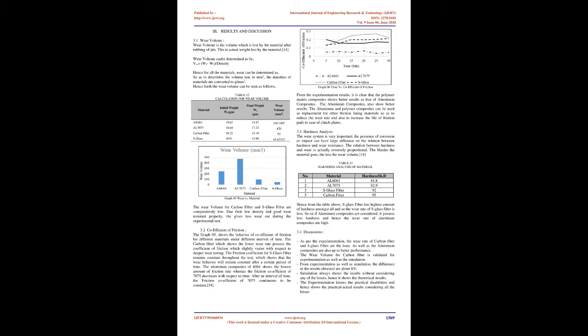The test stops after completion of the test duration. Remove the specimens, clean off loose wear debris, and note the existence of features on or near the wear scar such as protrusions, displaced metal, discolorations, micro cracking or spotting. Weigh the specimen and record the loss in weight. If the loss in weight is negligible, alternately the volume loss may be measured on the bottom disc.